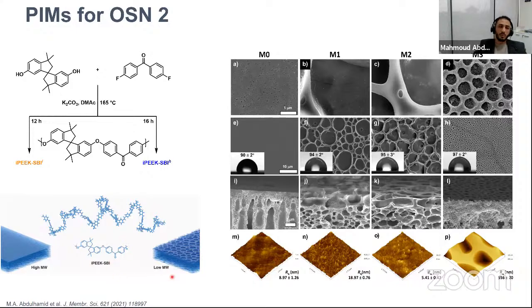However, when you have a low molecular weight polymer, a honeycomb pattern morphology is formed on the surface. This may result from some aggregation. We couldn't really find why we have it, but we tried low molecular weight, different concentrations, and different parameters, and we're always getting this honeycomb morphology. The presence of this honeycomb morphology enhanced the flux and the permeability of the solvent and gave better performance than the flat surfaces.